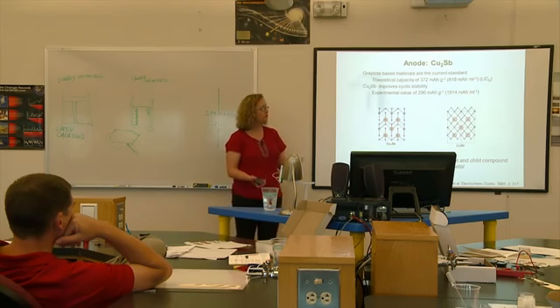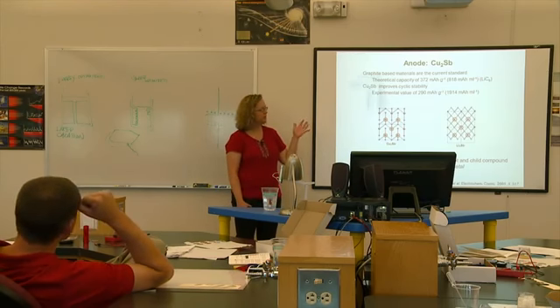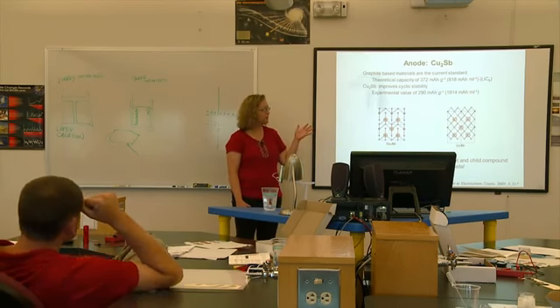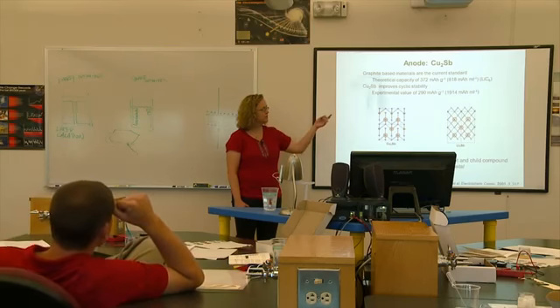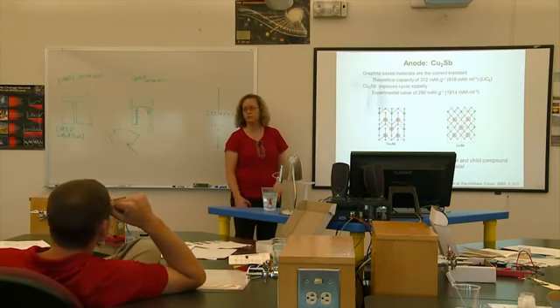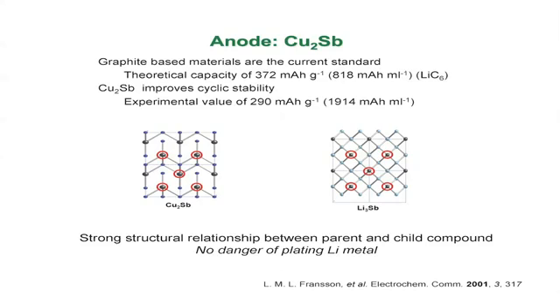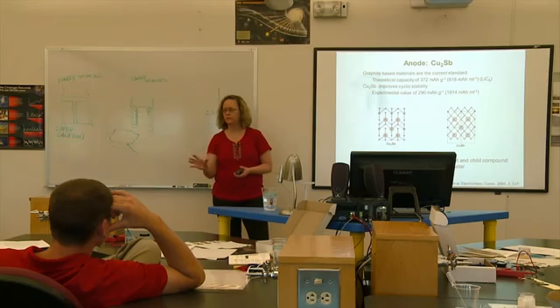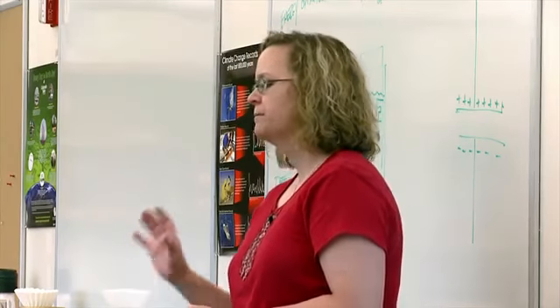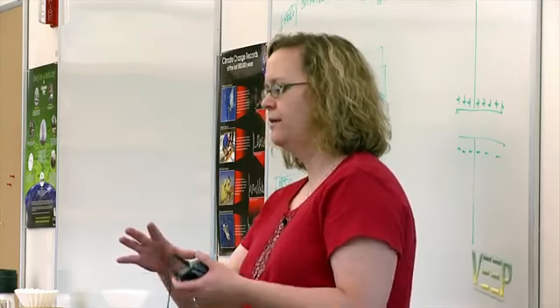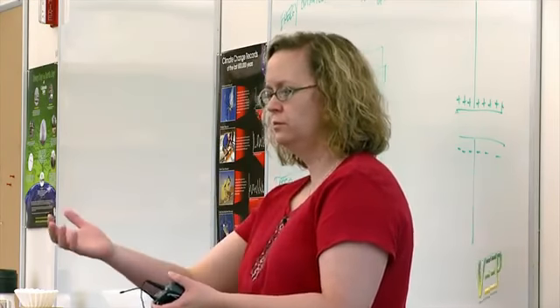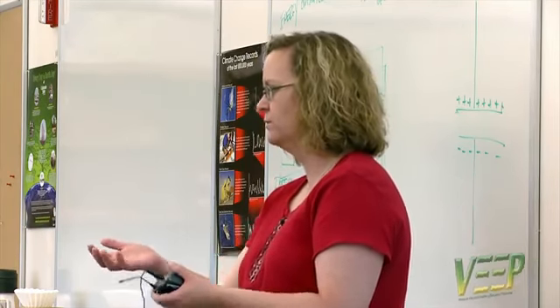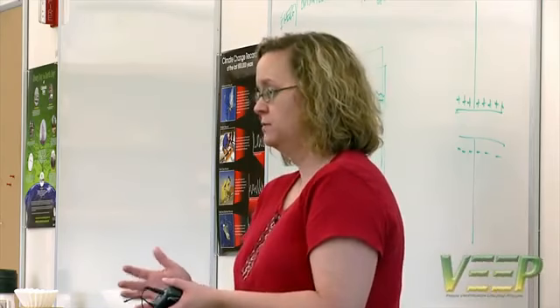But if you look at it volumetrically, graphite's at about 800 milliamp hours per milliliter, and copper antimonide's at about 1900. So it stores a lot more per unit volume, and we chose that intentionally because right now, all lithium-ion batteries are limited by their cathode material. There are no cathode materials that have really good capacity. So we wanted to have a structure where a lot more of the volume could be used to store cathode material, so we wanted an anode that would take up less space.